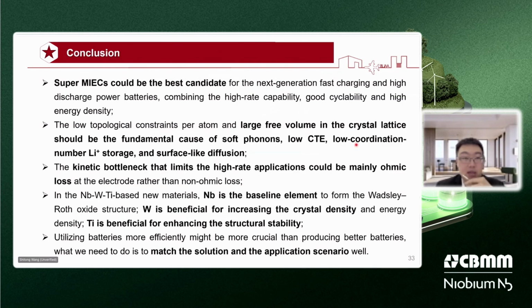And here's the conclusion. First, Super MIECs could be the best candidate for the next generation fast charging and power batteries. Second, the large free volume in the crystal lattice should be the fundamental cause of the soft phonons, low CTE, as well as the surface-like diffusion and the fast ionic transport.